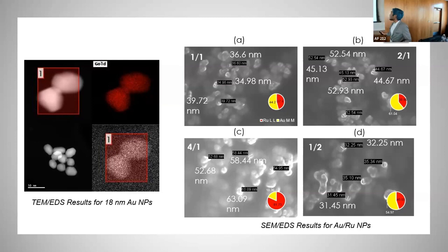And you can also see the overall composition is around 1:1 here and 2:1 here. Some of the particles are a little bit larger than the others, and that has to do with particle aggregation; particles typically want to aggregate and form larger particles over time.